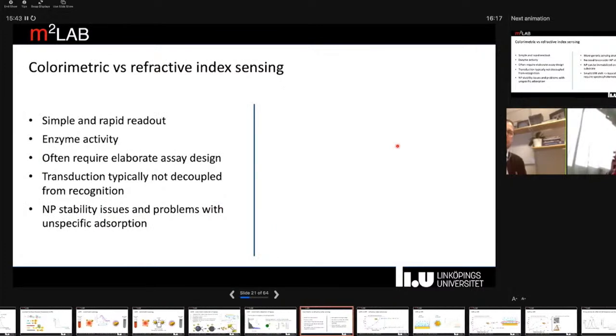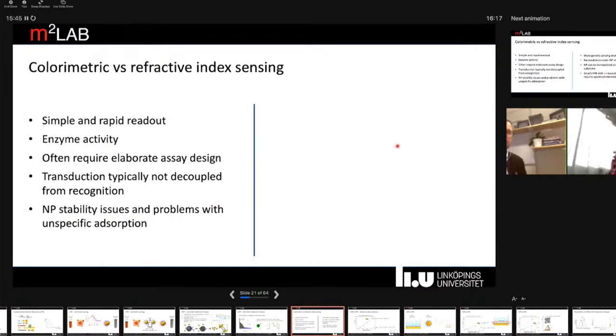So colorimetric sensors have the advantage that they are simple, and the readout is also very rapid and simple, because you don't need any elaborate equipment. Typically, they are naked eye detection. You can use them to monitor enzyme activity, as you saw in these examples, but they require elaborate assay design. And there's no generic way to make these assays. You have to redesign them for each analyte, which is quite tedious.